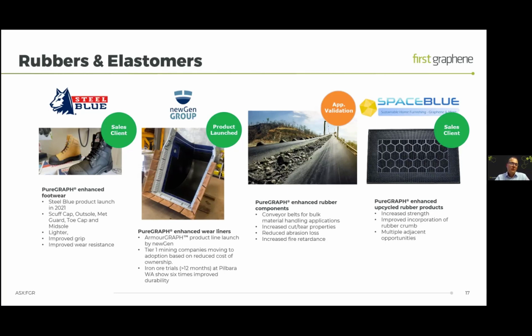In a recent trial we ran in a real life situation in an iron ore mine in the Pilbara, Western Australia, on the reclaimer bucket, which is shown in the image, the trial ran with the buckets for more than 12 months, and they demonstrated an improvement in durability of the wear liner with graphene by a factor of 6. So this means that by using graphene, you can extend the wear life of these products by up to a factor of 6.